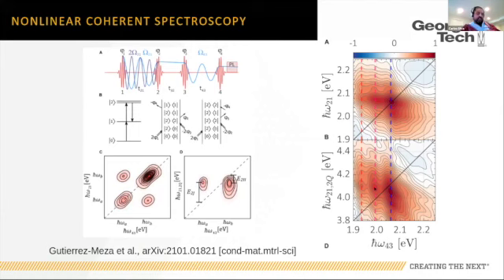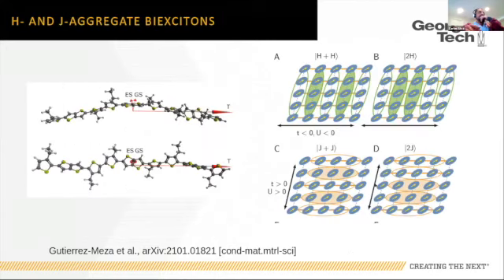How is this? Basically, we expect that if the interaction energy, this J, or here we call it a T in Eric's work, if T and U are the same sign, we will get a bound Biexciton. But they can be a negative T, a negative U, or a positive T and a positive U. And the really surprising thing is that what you have for a J aggregate is inverted for the Biexciton. If we have a J aggregate here, so we have an exciton dispersed along the chain, the way that the Biexcitons will interact will be with a flip side of the T's and the U's. So the J aggregate exciton wants to look like H aggregate Biexcitons. And conversely, the H aggregate exciton wants to feel like a J aggregate Biexciton.